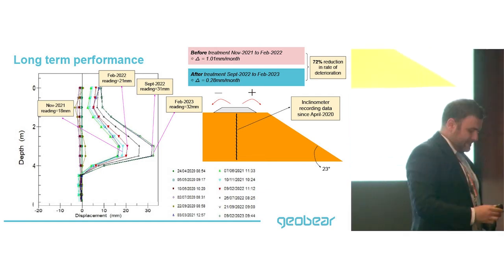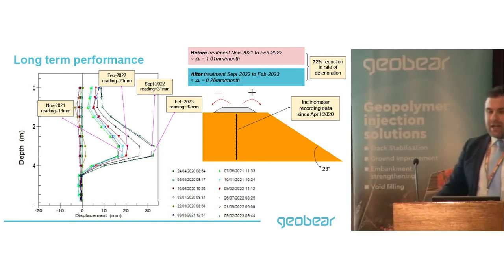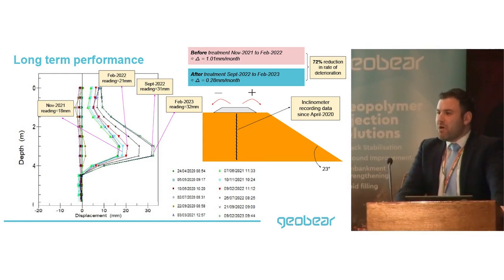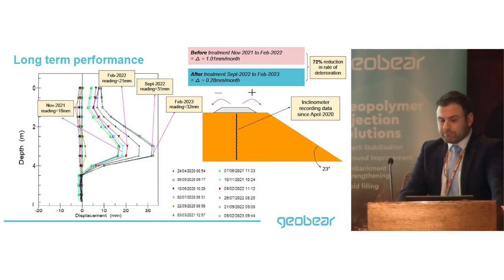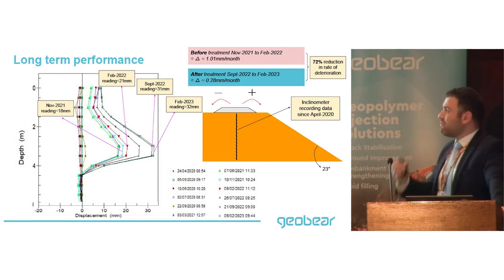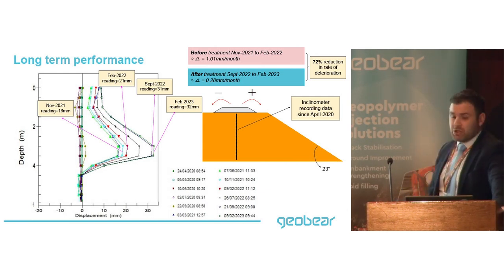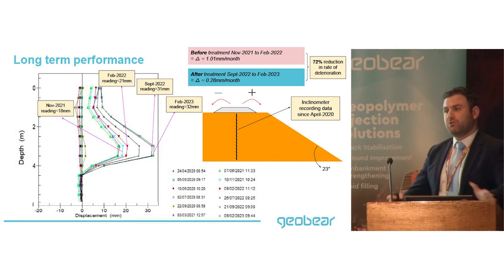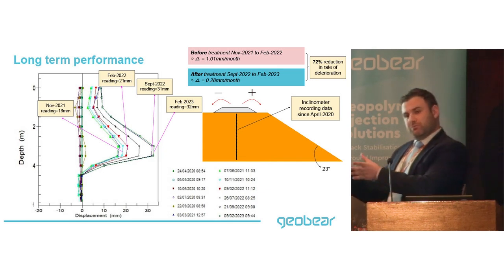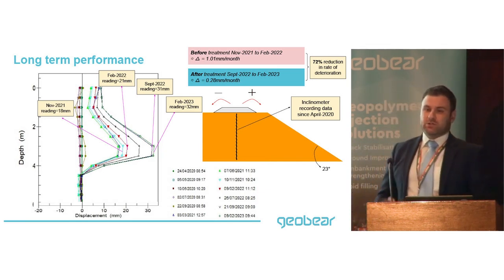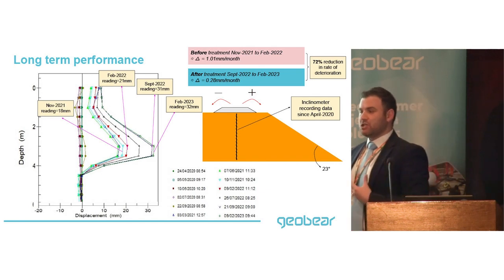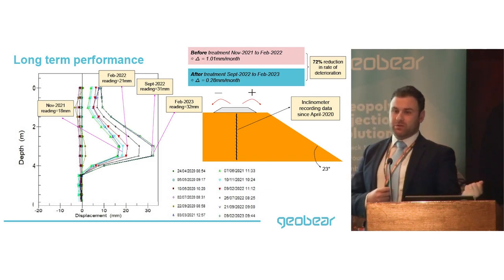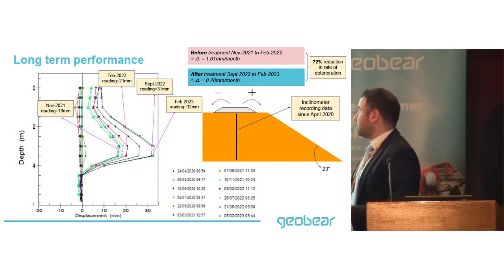If you take the delta of that, it gives you around 0.3 millimeter a month of movement, which translates to roughly a 72% reduction in the rate of deterioration. We were getting a similar percentage reduction in the tilt sensor, so that's basically making sense—it's matching up nicely with what you're seeing on the tilt data with the inclinometer data.